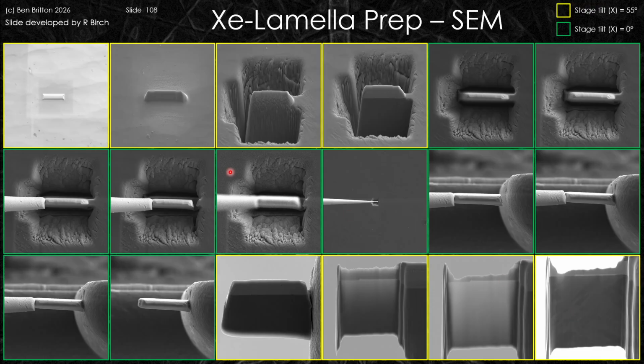And here are the steps shown in pictorial form. So the E-beam, I-beam cap, trenching, polishing, then effectively this is the polishing at 0 tilt. We then bring the needle in, we do the welding process, we then can do the J-cuts in this case. We can then cut it free in this case, and then we're going to effectively move this lamella upwards so it's out of focus, the sample remains in focus, and then we're going to move this sample out the way, bring the sample towards the grid, and then we can weld it onto the grid itself.